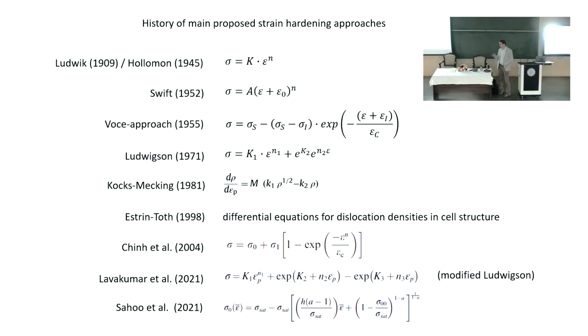Once this function is fitted, the obtained parameters can be used as an initial guess in the polycrystal simulation, because a polycrystal plasticity simulation is much more complicated than a fitting like here. There you have quite a number of parameters, and you have to do a full modeling, then plot and see it's not good, change a parameter, look again, no good — you do this for a couple of days, and with a bit of chance you get good agreement. I always got there, but it needed quite a lot of work.